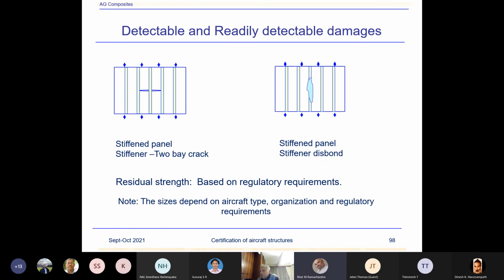So for methods for delamination and through-thickness damages, a lot of work has been done by lots of people. The difficulties come in the structures. You have a skin crack, and the spar is there. The spar also has to be broken on the flanges, and you must determine the residual strength of that. It doesn't become easy to analyze, and you can't keep on testing every configuration. So that means we must develop some reliable methods of analysis for the large damages. And that's what I was saying: hundreds of millions of dollars probably Boeing would have spent in developing the methods.